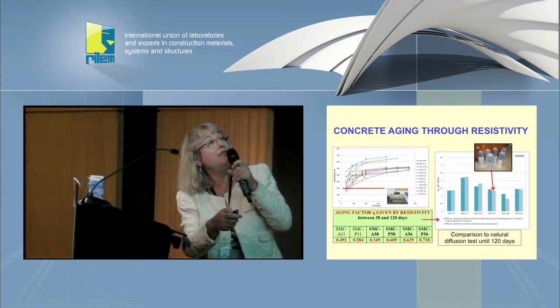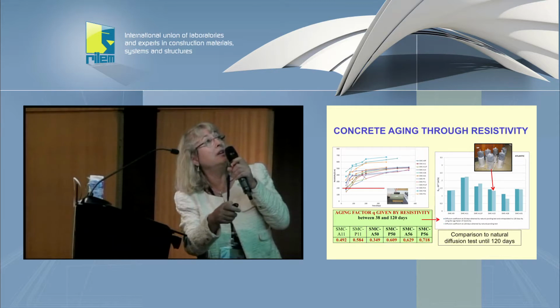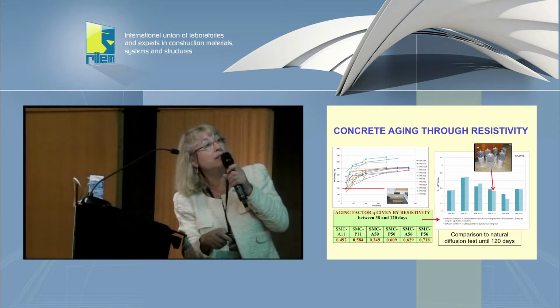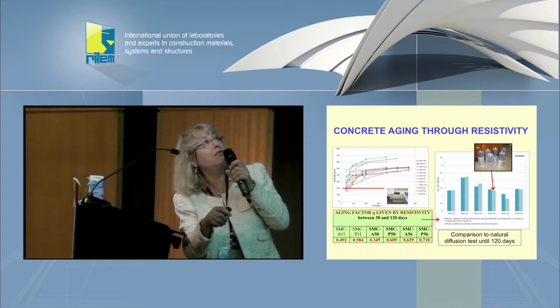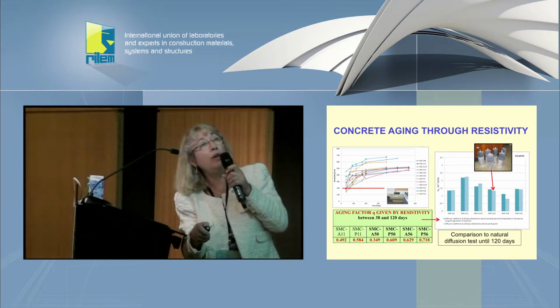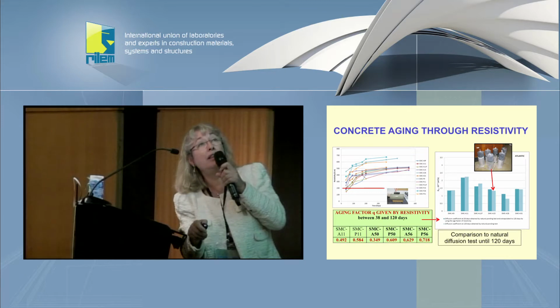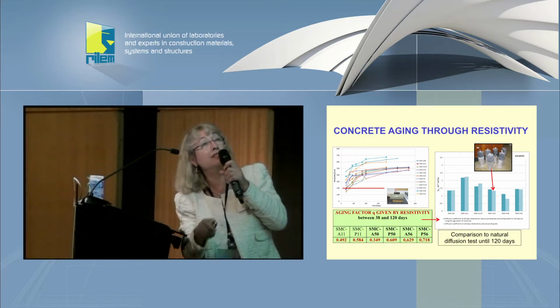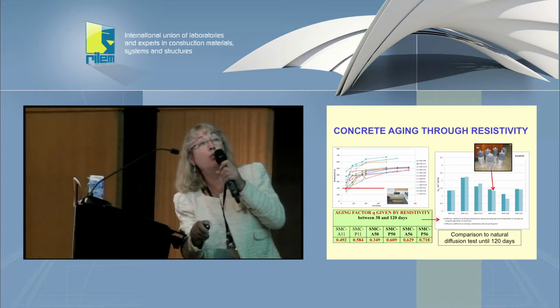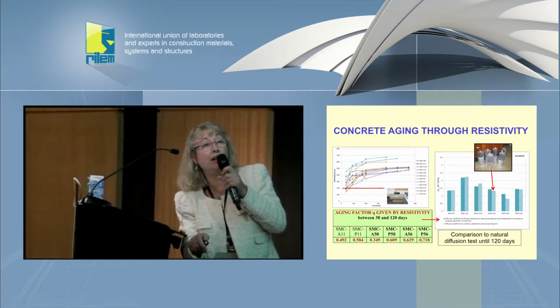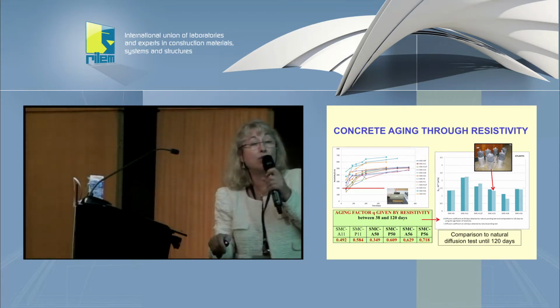And about the aging factor, it is possible just by monitoring the increase of resistivity with time. These are different mixes in the Panama Canal with the aging factors, and we compare the aging factors of the resistivity with those of the ponding test, having the salt water in contact with them. The aging factors obtained this way are very, very similar to having the concrete in contact with the salt water for longer times. This was until 120 days, that was the specification.